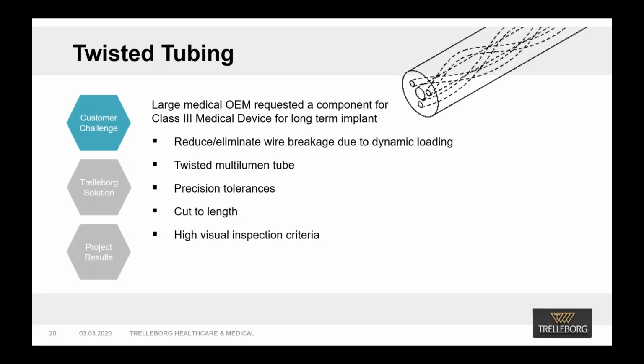The OEM approached Trelleborg to help in manufacturing a twisted tube that was expected to mitigate that device failure I mentioned, which was due to repeated strain from bend loading, where the cable lead assembly met their electronic housing. The challenges of twisted extrusion processing are in controlling the twist angle and the stability of numerous dimensions to tight tolerances. So these could be, say, 5, 6 lumen, all with very precise tolerance in an asymmetrical cross-section. So you can imagine all of those walls and all of those diameters with very tight tolerances.